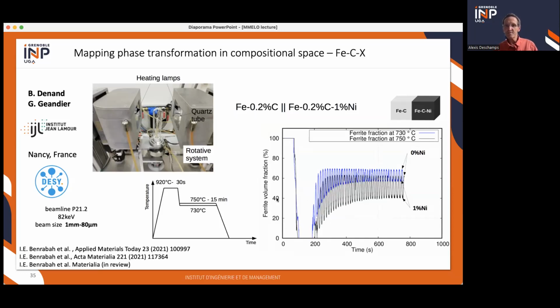So here, for instance, the evolution of ferrite fraction at 2 temperatures. And you get this kind of oscillations because you're oscillating throughout the composition gradient. And here, at the 2 ends of the oscillations, you get the 2 end compositions, carbon nickel-free and 1% nickel in this case. And in between, you have all the phase fractions for the intermediate compositions. So you get a lot of data here.